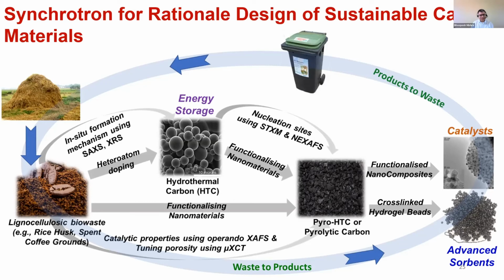And in all these processes, what you see is that for in situ formation mechanism, XRS and SAXS can be used. For nucleation sites, STXM and NEXAFS can be used. And of course, tomography, as I showed you examples for tuning porosity, and operando XAFS is super important for these. So there are many different synchrotron techniques, including XAFS, that can be used for rational design of these materials.